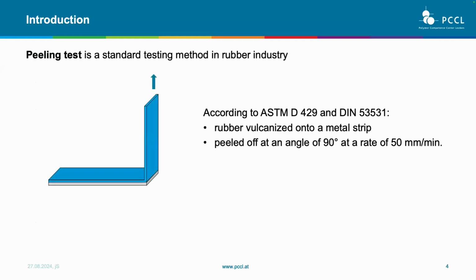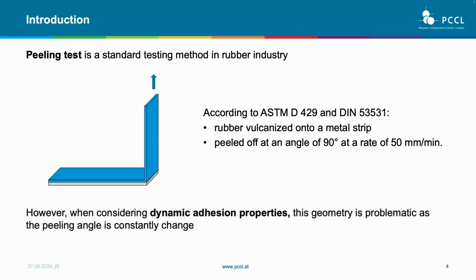Regarding adhesion in the rubber industry, normally adhesion is assessed through the peel test, which is quite common and easy to use, especially at 90 degrees. This is a typical example. What is important, though, is that during the test, to have reliable parameters, the angle of peeling should be constant and kept under control. Since we wanted to study cyclic adhesion, clearly the angle during cyclic loading cannot be maintained constant unless with a really complex setup and testing.